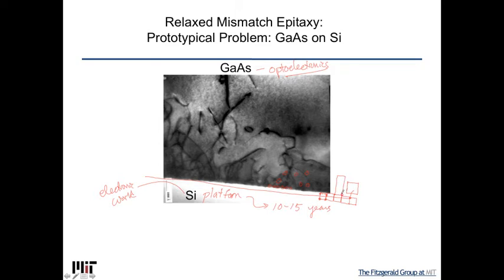Because the atoms don't know what they're doing, they come down and line up with the template. And then what they find out is, oh my goodness, I'm much more squeezed than I should be, and it wants to pop out and relax like that. Well, when it pops out and relaxes like that, it creates a defect in the middle, which are these black lines. These black lines are dislocations.